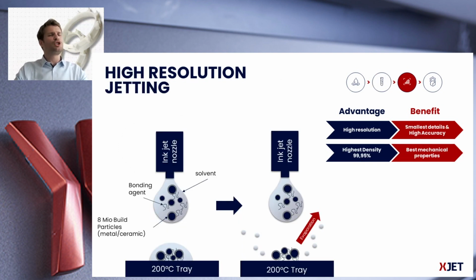High resolution jetting. We are printing at 1,440 drops per inch in terms of resolution. We are printing 120 million drops per second maximum. And we are printing in very thin layers of around 8 micron. And this high precision and high resolution leads, of course, to the potential of printing very small details and also printing highly accurate. But on top of that, with these nano or submicron particles and the precision, we can create a density of more than 99.95%, which on the one hand leads to fantastic mechanical properties of the part that are comparable or sometimes even better than traditionally made ceramics or metals.